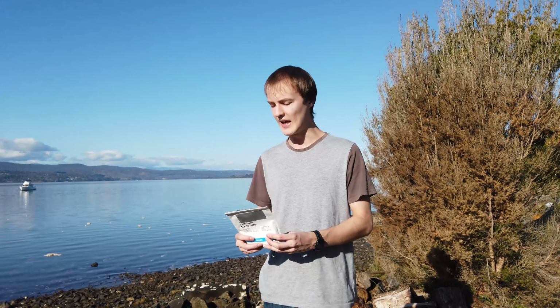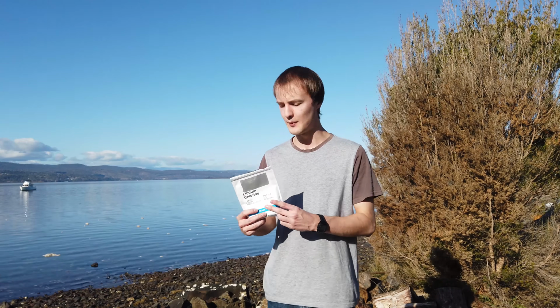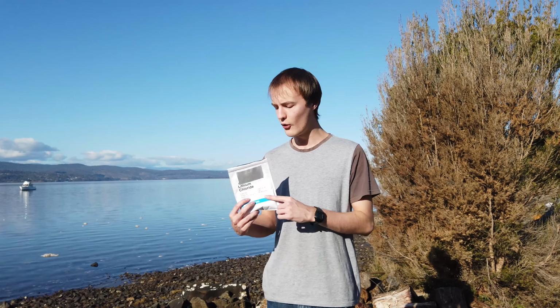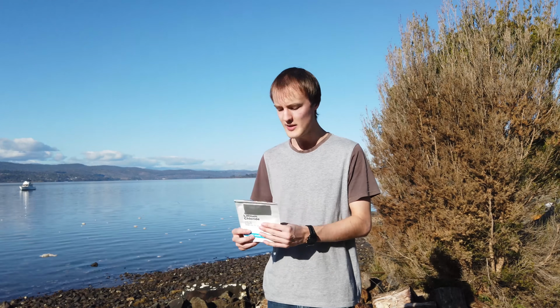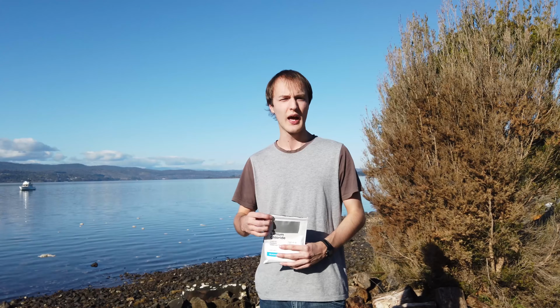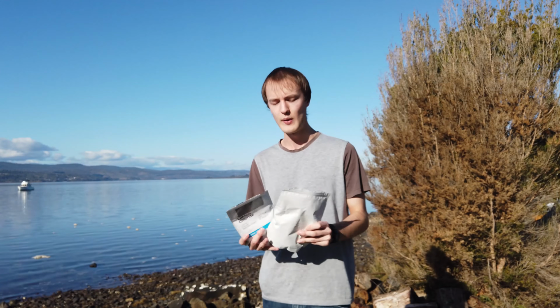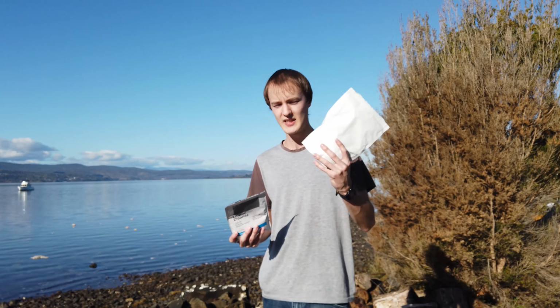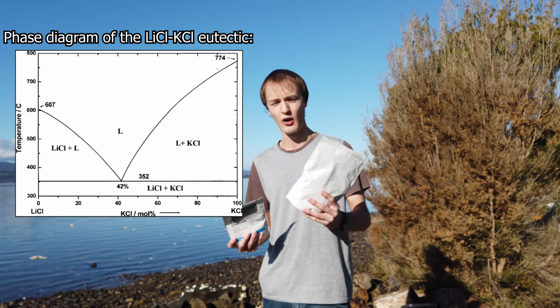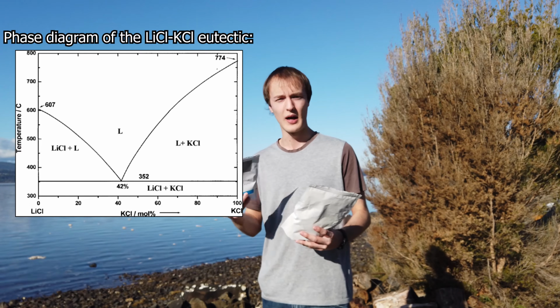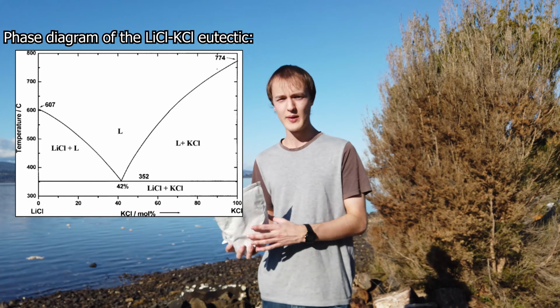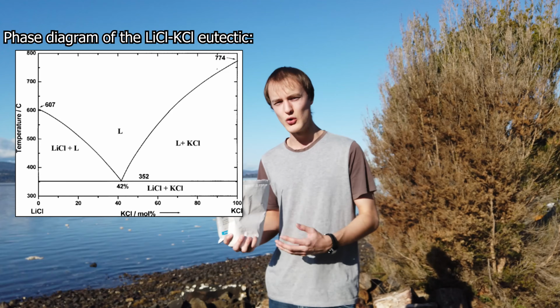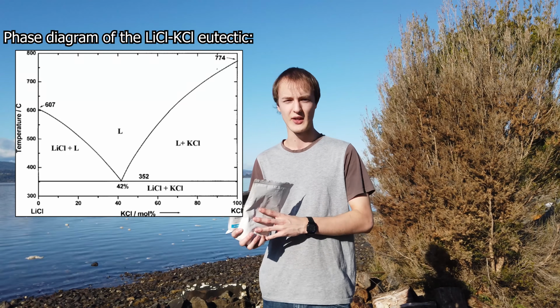Luckily, industry has the answer for mitigating the risk of lithium catching fire in the process by lowering the melting point of the lithium chloride, and we can do that by using a eutectic mixture of two salts, that being lithium chloride and potassium chloride. So if we mix these two together such that the potassium chloride is at a concentration of 42% by molar ratio, we can lower the melting point of the lithium chloride to around 352 degrees Celsius.